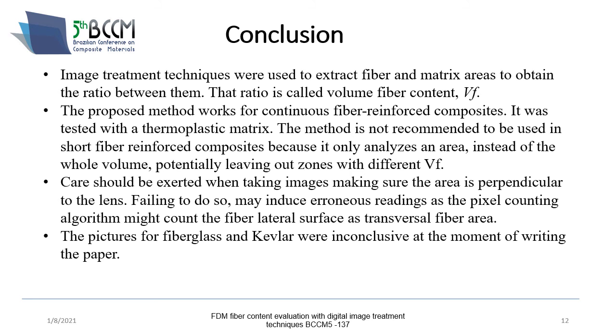And this method is not recommended for short fiber reinforced composites because it only analyzes a transversal area instead of the whole volume, potentially leaving out zones with different volumetric fiber fraction. Also, care should be exerted when taking the image, making sure that the area is perpendicular to the lens. Failing to do so may induce erroneous readings, as the pixel counting algorithm might count the fiber lateral surface as transversal fiber area. Finally, the pictures for fiberglass and Kevlar were inconclusive at the moment of writing this paper.